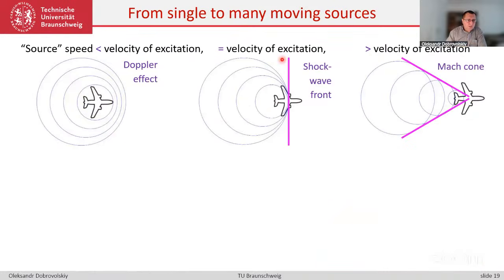And in addition to that, one has to consider three different regimes. Basically, if the source moves at a velocity which is lower than the velocity of excitation, we would just have a Doppler effect. It was already investigated in the first experiments of magnon-fluxon interaction. In the opposite limiting case, when the velocity of excitation is lower than the velocity of the moving source, we would have a Mach cone, as we have seen, for instance, for water waves, the Kelvin wave. We can also expect this for magnons and fluxons, but the results I'm going to present today are related to this self-synchronized regime, when the source speed is equal to the velocity of excitation. This corresponds exactly to the shock wavefront synchronization.